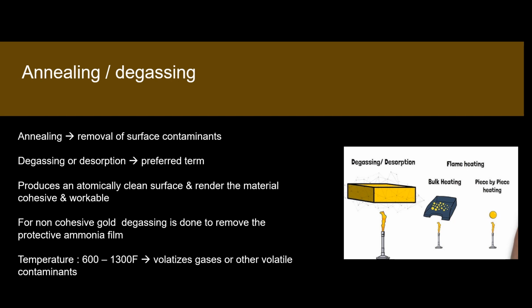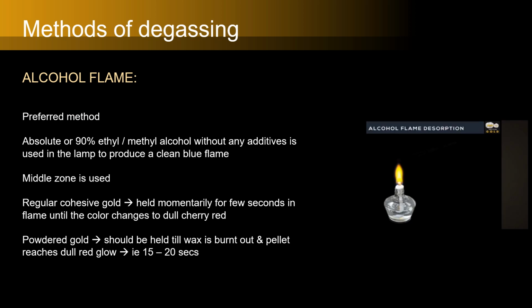So when you perform this procedure, that is annealing, it produces an atomically clean surface of gold and renders the material in a cohesive or workable form. So for a non-cohesive gold, degassing should be done and it helps to remove the protective ammonia film, and it is carried out at a temperature of 600 to 1300 Fahrenheit so that it volatilizes the gas or other volatile contaminants. So there are various methods of degassing.